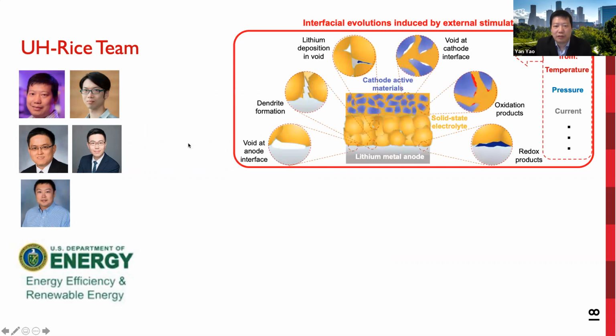So the failure mechanism of a solid-state lithium battery may be briefly attributed to two main causes. One is the interfacial resistance increase, and the second is lithium dendrite growth. The resistance increase may be attributed to electrolyte decomposition and void formation at the interface, which happens at both the cathode-electrolyte and anode-electrolyte interfaces.